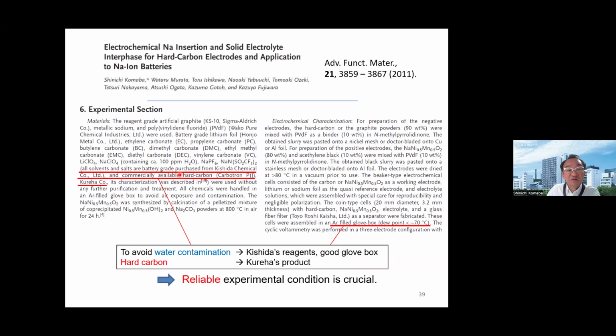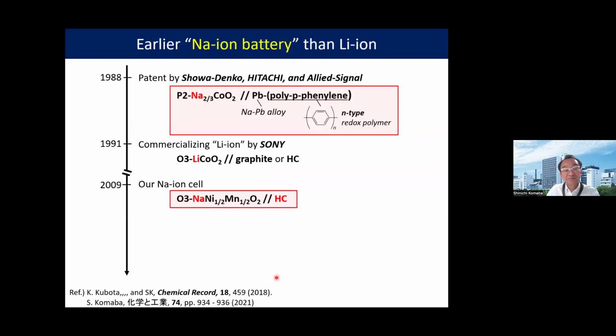And finally, we concluded that Kishida Chemical Corporation's battery grade electrolyte solution is the best choice for sodium insertion electrochemistry. And for hard carbon, after careful comparison, we selected hard carbon from Kureha Chemical Corporation. Then we succeeded in demonstrating highly reversible sodium insertion and extraction, not only in carbon, but also in layered oxide. We demonstrated this reversible sodium ion cell.